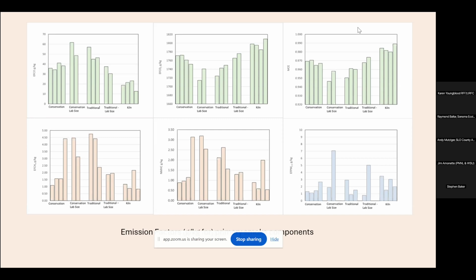And then for the methane on the lower part there, that was kind of a mix. Generally the methane was a bit lower for the kiln, but we had a couple of fires that were much higher than the others, so that kind of messed up the mix a little bit. For non-methane hydrocarbons, which are a sum of all the hydrocarbons except methane, it's kind of similar to methane: the conservation was about the same as the kiln and the traditional. It's hard to really see where there's a lot of difference between them.